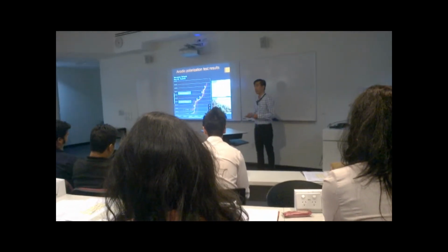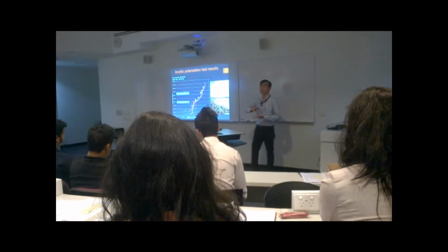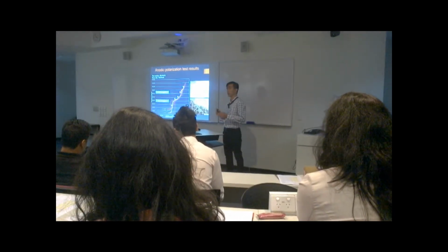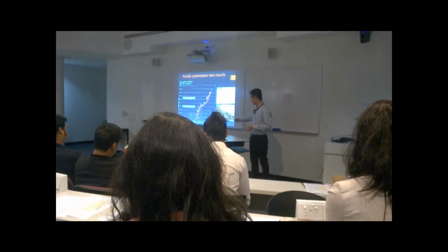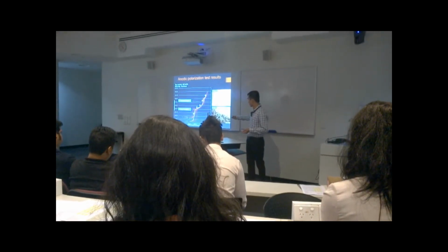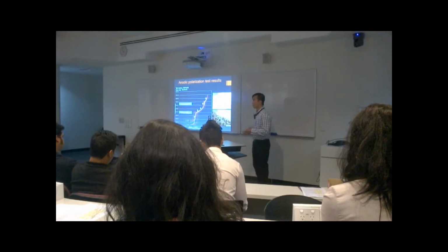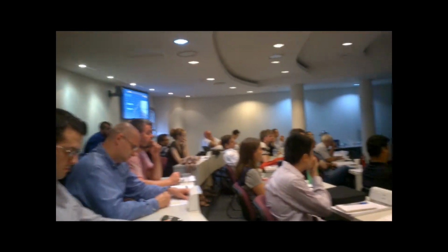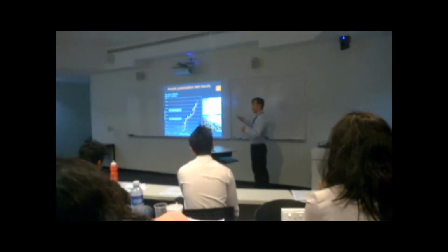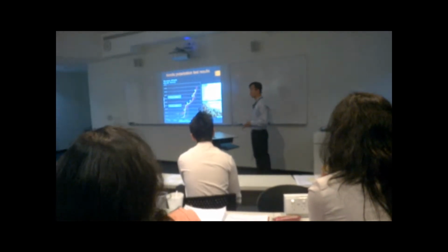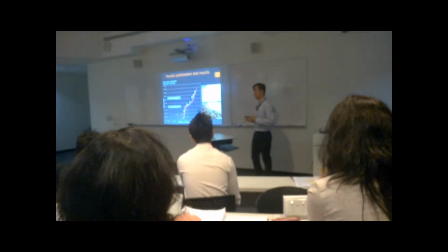Passivity is when the metal can form a stable oxide component on the surface to stop it from further corrosion. And you can see the current doesn't change much at all with the changing of potentials. Examination of the microstructure before and after the anodic polarization test shows that the carbide in here is really tight, and you can see after the test all the carbide shows in the black region here. So the corrosion attack actually occurs on the carbide. The matrix next to it, you can see it. It means that corrosion attack on the matrix is actually less than on the carbide.